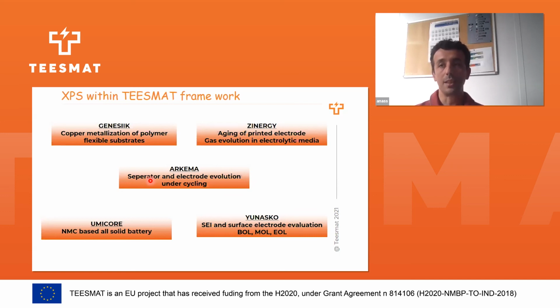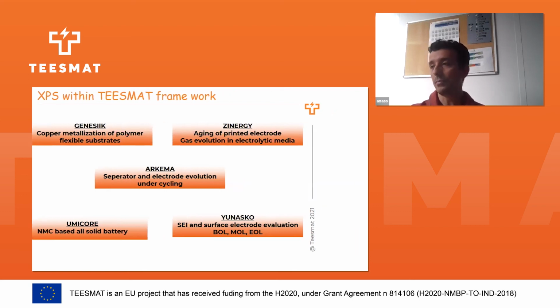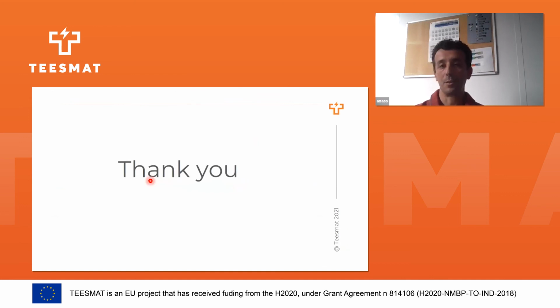The first one was copper metallization of a polymer substrate. The second one was aging of a printed electrode and seeing some gas evolution and reactivity through the electrolytic media. Arkema was a separator case. Umicore was their cathode materials, and Yunasko was the SEI growth at the beginning, middle, and end of life of the electrode evolution. And thank you very much for your attention.